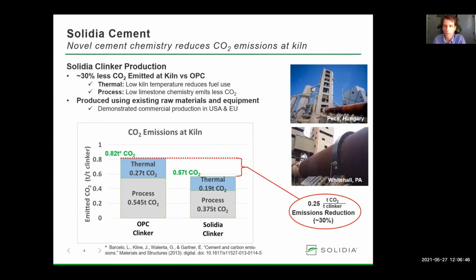A bar graph below illustrates savings between OPC clinker and Solidia clinker. Total savings for Solidia clinker production is 0.25 tons CO2 per ton of clinker relative to OPC. I should note that for both cements, I'm reporting emission numbers for clinker, and I'm not considering the addition of things like limestone or gypsum.